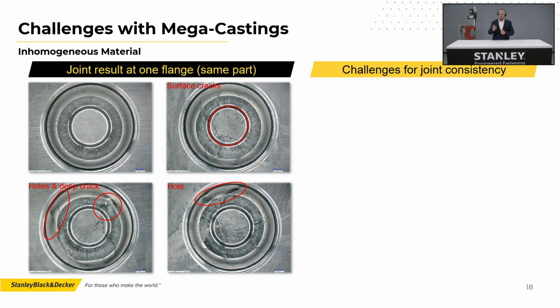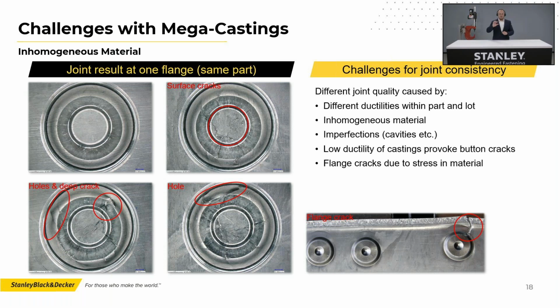And one addition that you can also see or find is the closer you get to the flange edges, you can have flange cracks. But this is also not always the case, but the closer you get to the flange edges, the higher the risk you get a crack. So when you aim for a perfect button without cracks, it seems that there is more stress in the surroundings of the material, so that the chance is higher to get a flange crack. So with these results, you might actually think about redesigning the flange size, and some of the OEMs are already doing that because they are aware of this issue, right? So this is the last issue that I can show you here on inhomogeneous material.